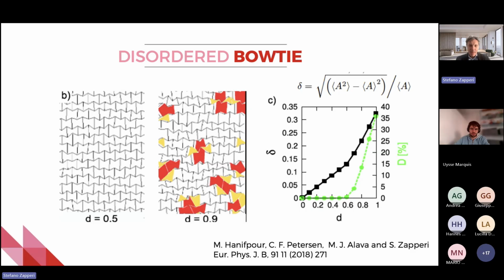What we did in this paper, together with some collaborators almost 10 years ago, is scramble a little bit this perfect bow tie. Here it is a little scrambled. Here it is even more scrambled. The difference between left and right is that here we also introduce some topological defects. Here, they're all cells that have 6 edges. Here, you start to have cells with 5, with 7, and so on. Then you can quantify by some parameter delta how much disorder you put, or how much fluctuation you have in the metamaterial.